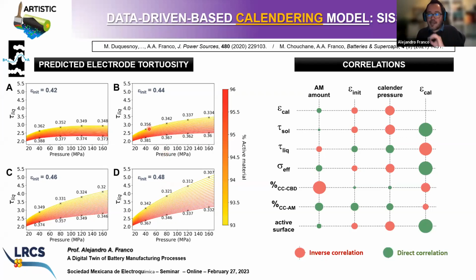And you can also see that the degree of impact of this calendering pressure on the final tortuosity of the electrode depends on the initial porosity of the electrode, I mean the porosity the electrode has before the calendering, and also depends on the electrode formulation, right? And I believe, once again, that this kind of result arising from machine learning can be very useful for guiding technicians and engineers working in prototyping lines and in pilot lines before the production of lithium-ion battery cells.